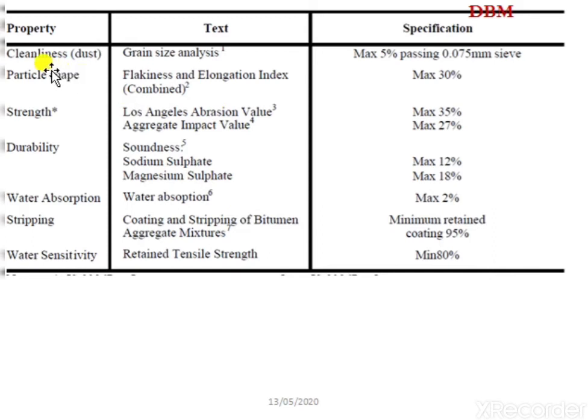The first property is cleanliness. To determine the cleanliness, the test conducted is grain size analysis. As per the MORTH specification, the cleanliness should be a maximum of 5% passing the 0.075 mm sieve. The second test is particle shape. The particle shape test is conducted using the flakiness and elongation index, and here the maximum value should be within 30%.